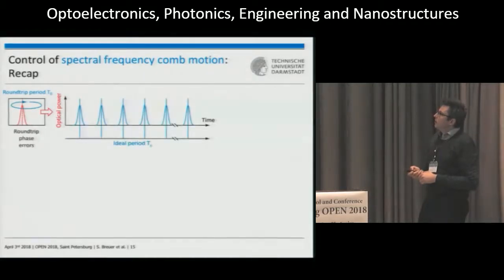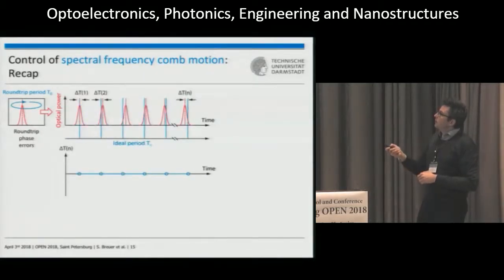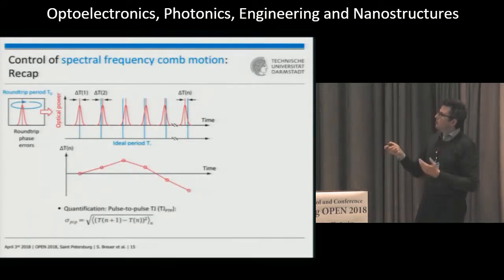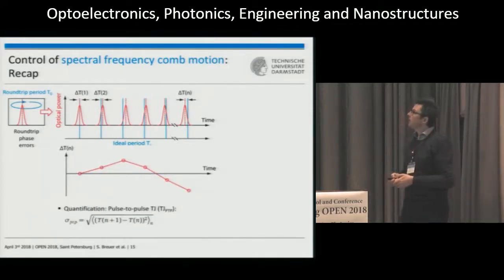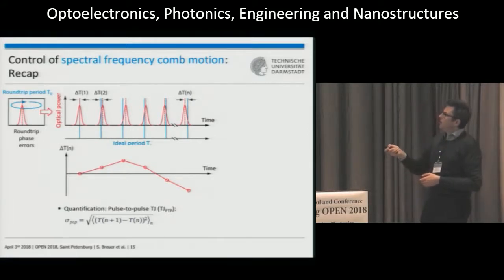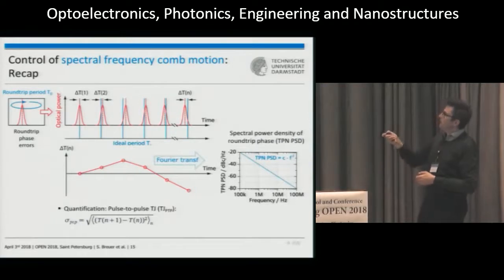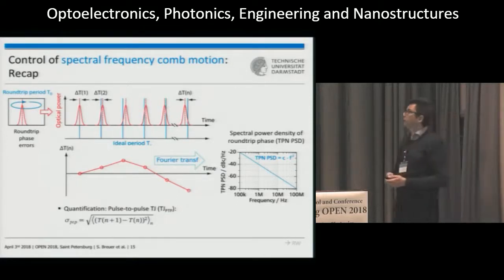So let's just recapitulate. We have seen these pulse deviations with respect to the ideal period, and these basically add up as small deviations in time. So this is basically a random walk process, and this can be quantified by the pulse-to-pulse timing jitter. As we have seen, just Fourier transforming this time signal into the radio frequency domain gives us the 1 over f squared dependence, which is also valid for the von der Linde method for a directly modulated laser.